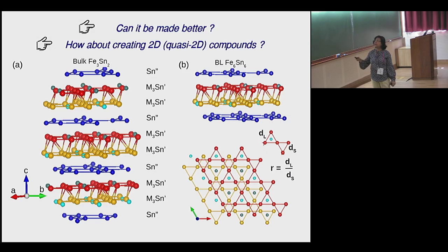You have a bilayer Kagome of this iron, in this specific case it's iron, and that is sandwiched between some tin layers and that are stacked on top of each other. From there, what we created is a bilayer structure, which is a single bilayer of this Kagome layer, sandwiched by these tin layers. And the Kagome layer, if you look at the interesting feature, consists of two different triangles, one a large triangle and a small triangle, and let's call the ratio of this large to small some parameter r.